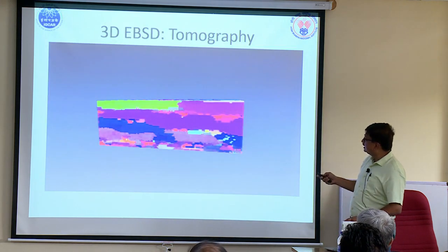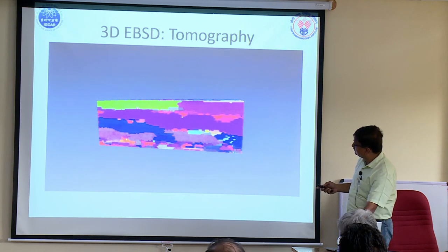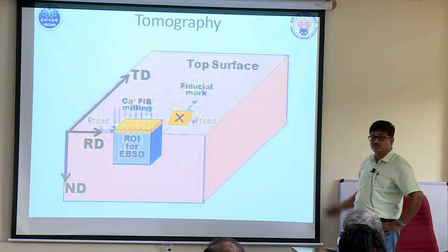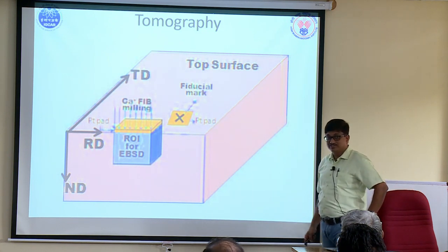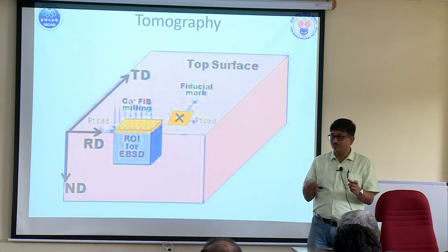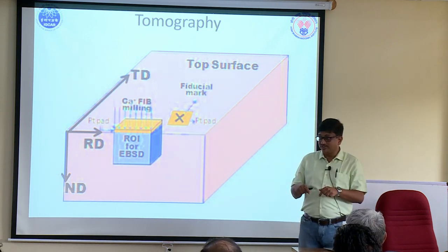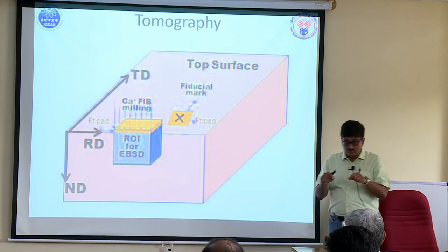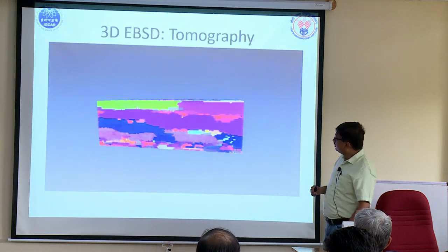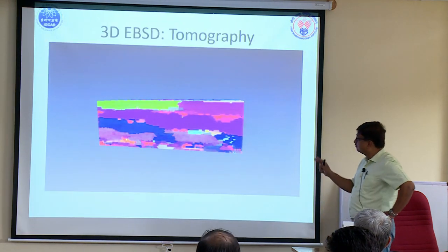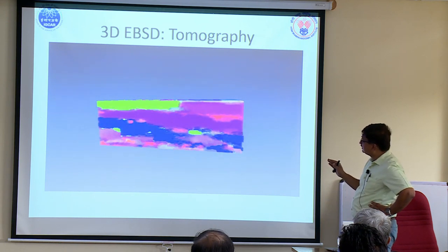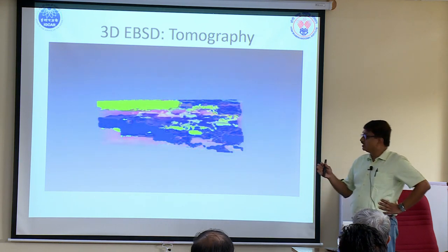The other thing to note here is, put some 1 or 2 of these cross marks. They are called fiducials, and teach your program to always look for them as and when they rotate, because it is those fiducials which are used to align your sample. Okay, that's very important. So this is what is generated. If you look very carefully, I think it's running. Yeah, it's running. Yeah, so these are all the things.